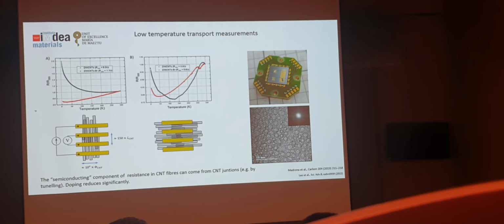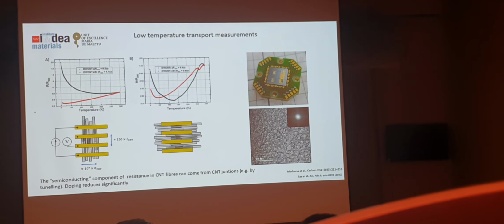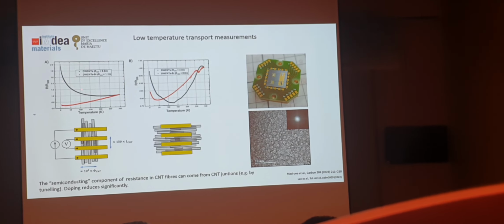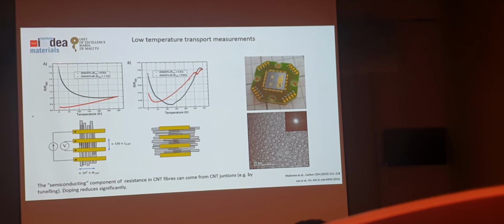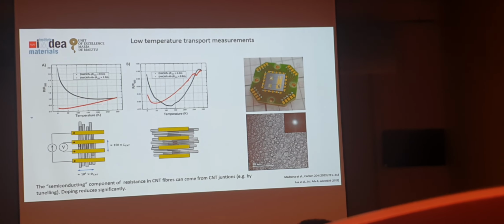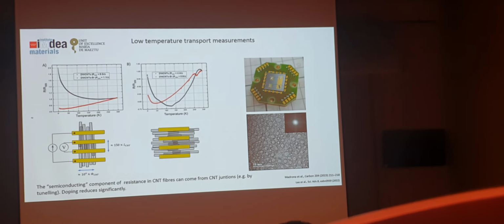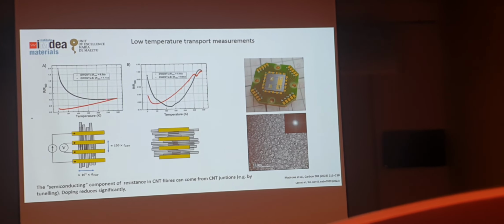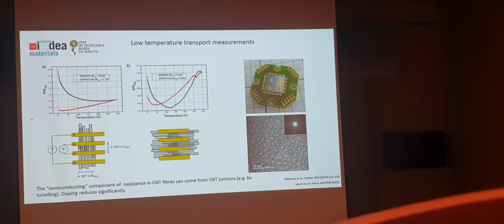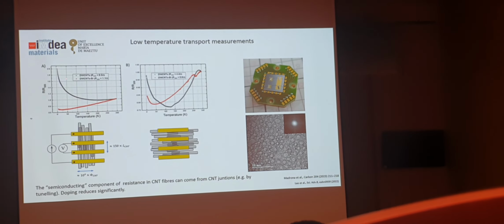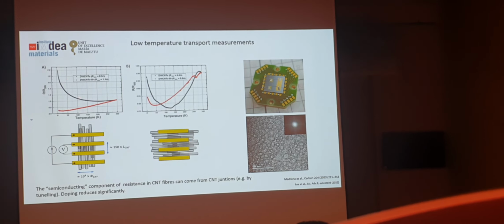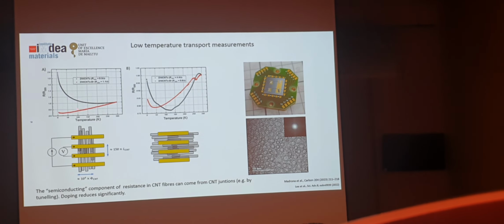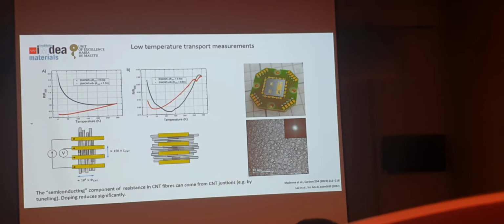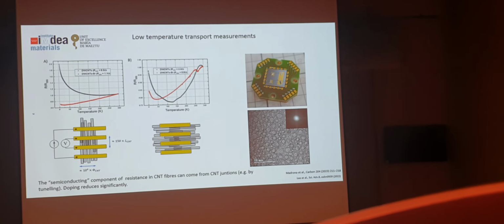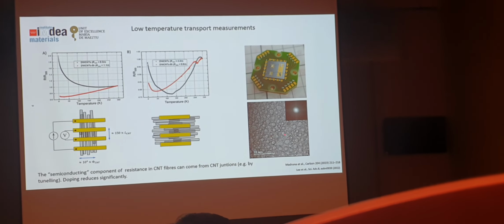So the second insight we got into this came from other work on doping we did. And essentially we took a fiber or film and we did some field-effect transistor measurements with and without dopants. And some people have observed this in the past. So essentially, if there's no dopant, the material is a combination of a metallic resistance and a more semiconducting resistance. And if you dope it, you essentially suppress that semiconductor-like behavior. And it was more or less believed that the dopants would essentially increase carrier density, just like they do in a semiconductor. But I'm not so sure about that, because first of all, if you think of a real fiber,